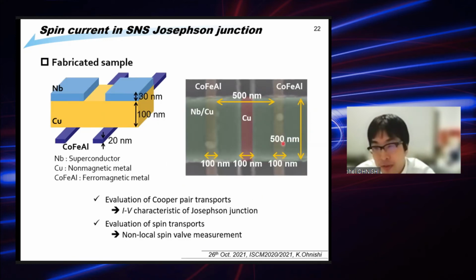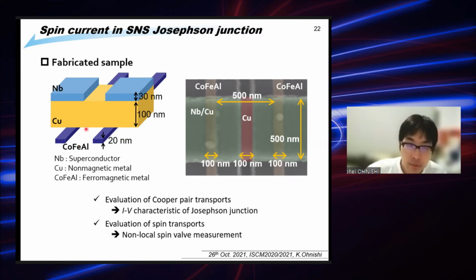This is the actual fabricated sample. These two orange wires, cobalt iron aluminum, are the ferromagnet, as in the schematic shown here. Then this green area is the niobium copper bilayer, and only this red area has only the copper layer. It's just a bridge for the two ferromagnets and the niobium, these two layers. In this structure, we can evaluate the Cooper pair transport by the characteristic of the Josephson junction, on the top side. And also we can perform the evaluation of the spin transport by the non-local spin valve measurement on the bottom side.